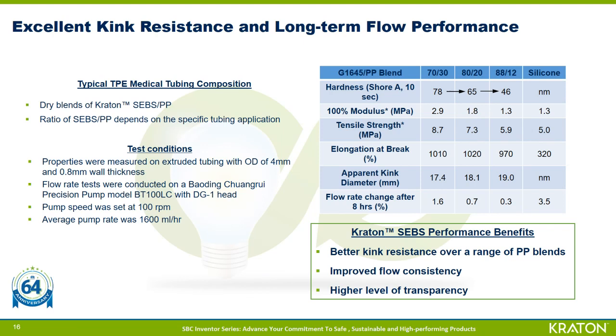You can see that the flow rate change is very small, and it definitely depends on the tubing hardness, which depends on the tubing composition, but it is much smaller than the change that is seen in a silicone tubing, for example.